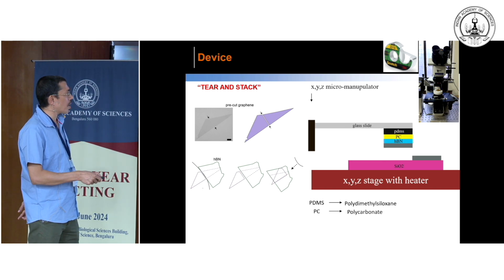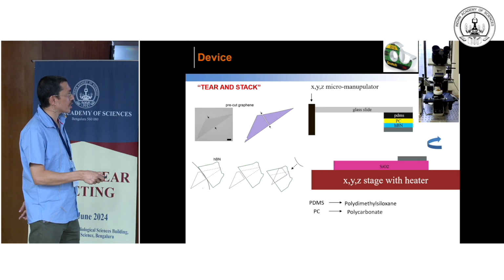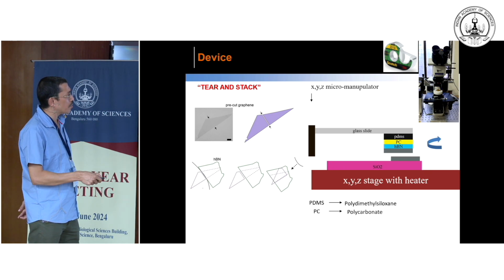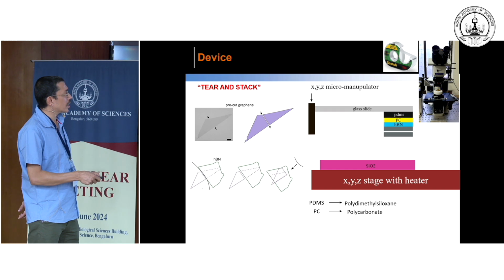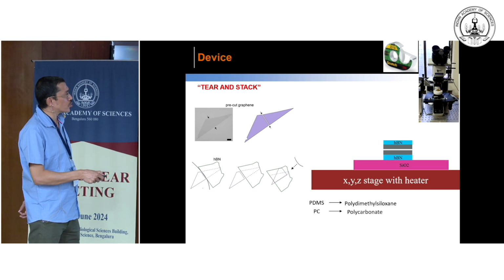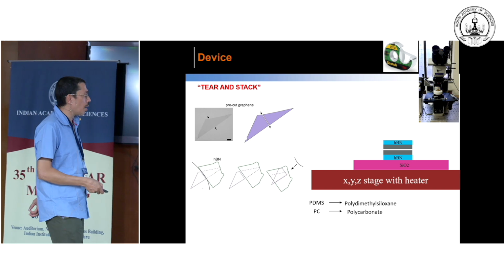The black part is one graphene sheet. Basically we cut it in 2 pieces. We give a relative twist angle between them, and that's the way we make a twisted bilayer. And this twisted bilayer is encapsulated between boron nitride and so on. So let's go to the measurement now.